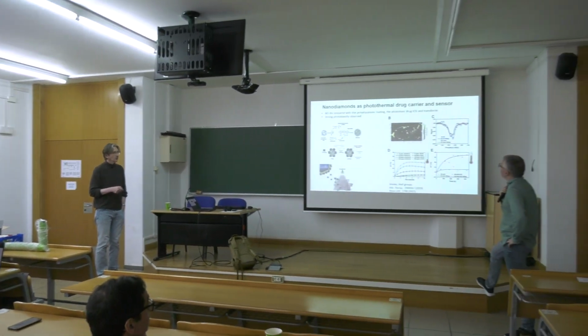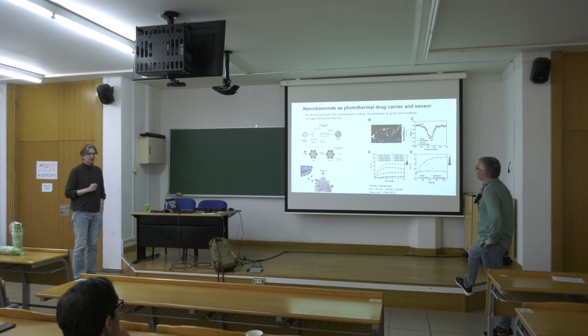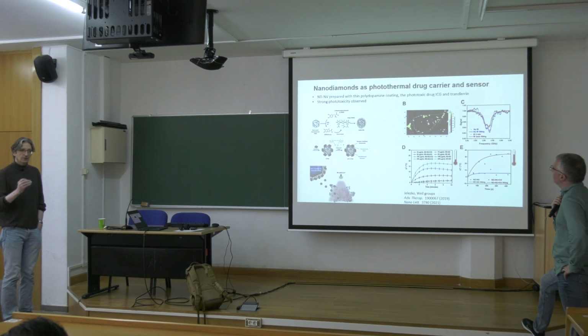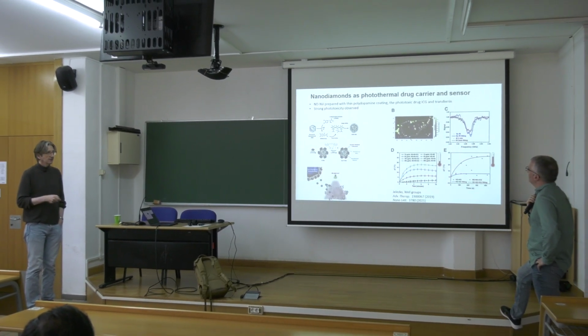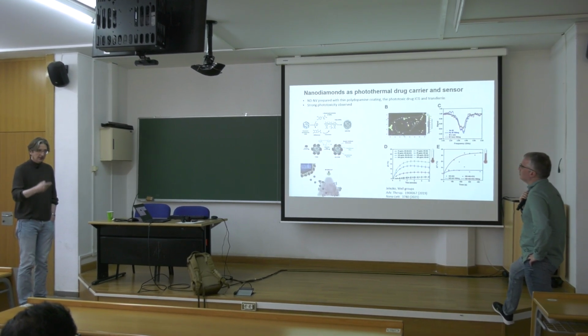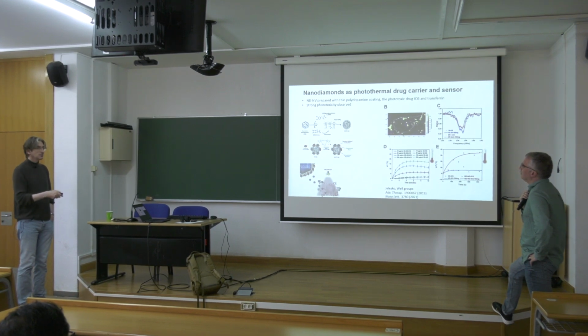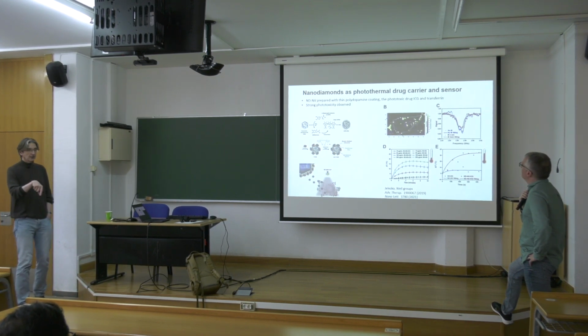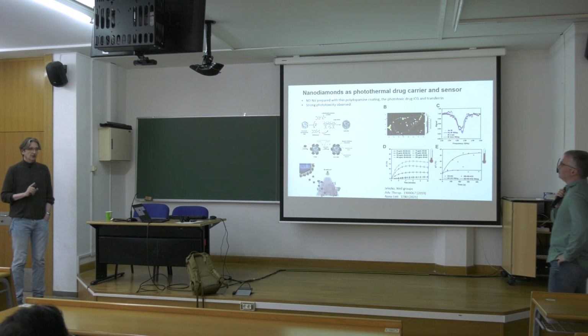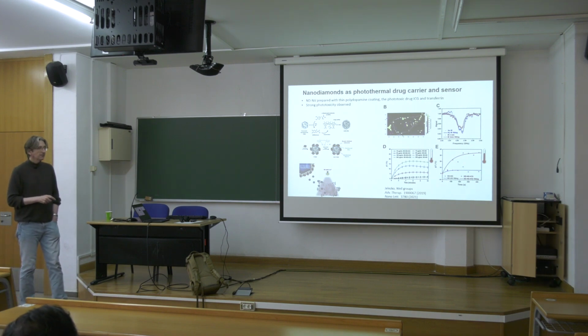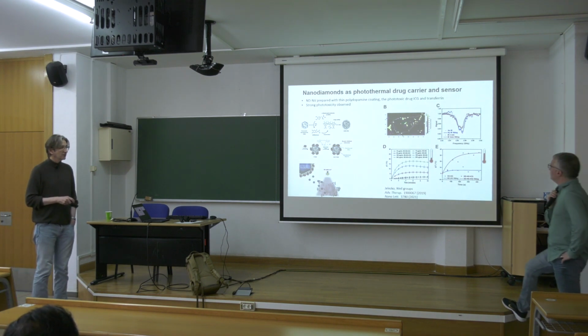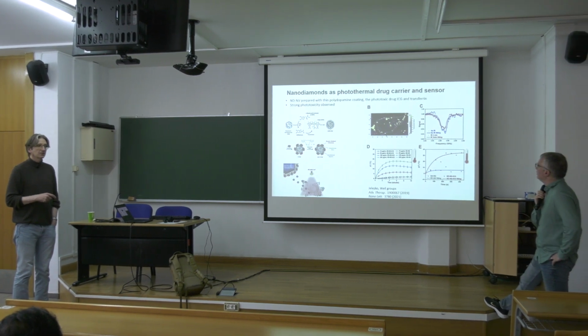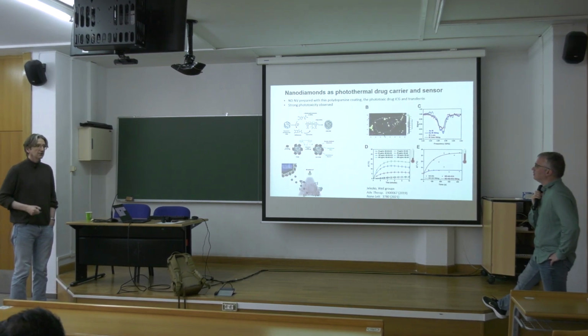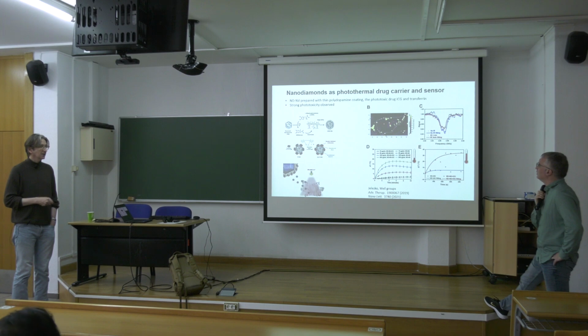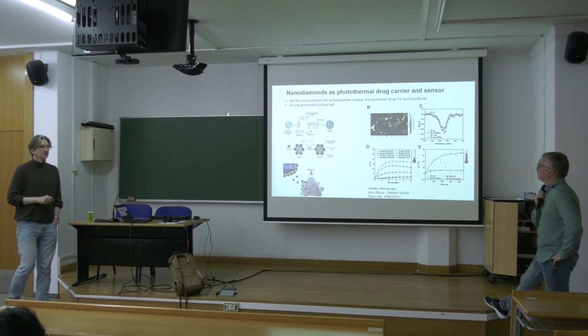After this, the coating, which also responds to infrared illumination, can be brought to some temperature, and then after reaching some temperature, the drug is released, and we can see this in measurement of phototoxicity of the whole cell line. That was not shown. And that was correlated with the temperature that was observed inside of the cell. So it was possible to correlate the action of the drug with the temperature of activation.